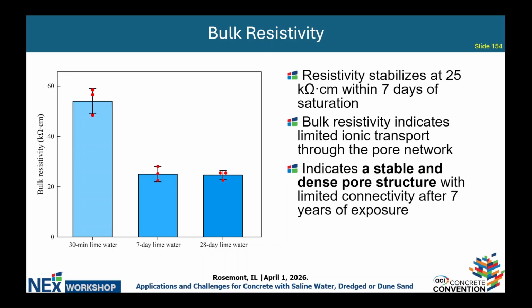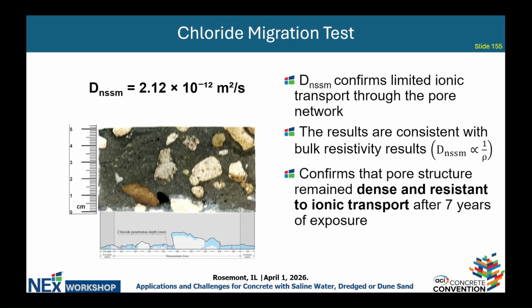We also confirmed the result of bulk resistivity with the chloride migration test. The chloride migration test showed a low non-steady state migration coefficient, and this can be correlated to bulk resistivity, where the higher the resistivity, the lower the migration coefficient. So we can, again, indirectly indicate the good chemical resistance of this system after 7 years of real marine exposure.